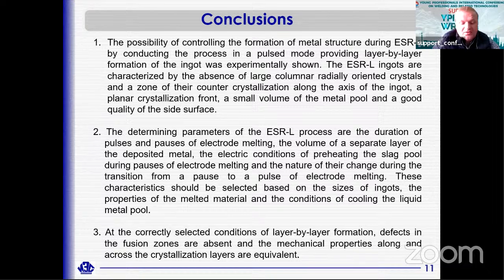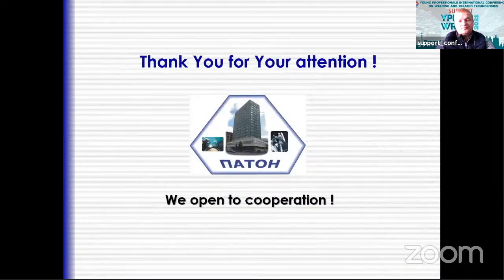In conclusion, I will not dwell on everything, I will only say the most important thing. The possibility of controlling the formation of metal structure during ESR by conducting the process in a pulsed mode, providing layer by layer formation of the ingot, was experimentally shown. At correctly selected conditions of layer by layer formation, defects in fusion zones are absent, and the mechanical properties along and across the crystallization layers are equivalent. Thank you for your attention. Can you ask me?